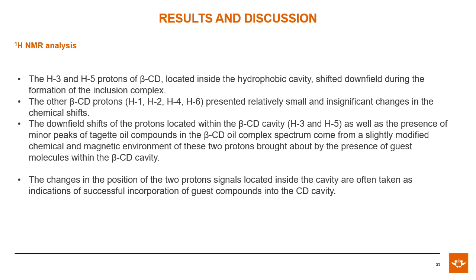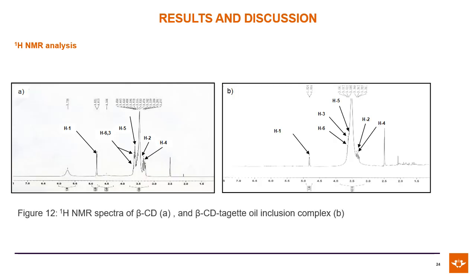We also used nuclear magnetic resonance spectroscopy to analyze our inclusion complex. The successful preparation of our inclusion complex was confirmed by the shift to downfield regions of H3 and H5, which are located in the hydrophobic cavity of beta-cyclodextrin. It was also confirmed by the presence of minor peaks of tagette oil on the proton NMR spectrum.